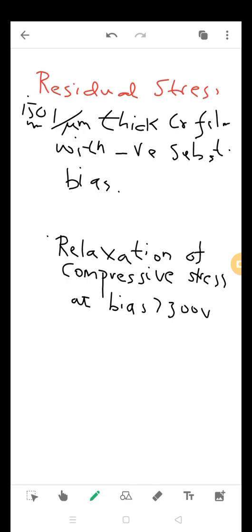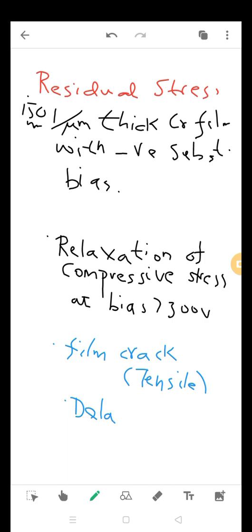Now, the residual stress that we usually have in films has negative effects. Film cracking may take place due to this residual stress, mainly due to tensile stress. Due to compressive stress, the negative effect is delamination. That means the adhesion between the film and the substrate weakens, and the film gets separated from the substrate. So two different types of stress have two different types of effects on the film. When we are dealing with films used in microelectronics, we need to reduce this residual stress, otherwise device performance will go down.